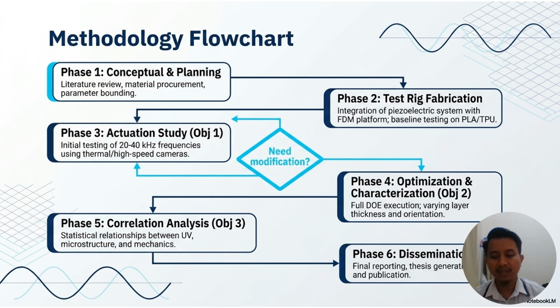Here, FDM-printed SMP samples are subjected to UV frequency from 20 to 40 kHz, with shape transformation recorded by thermal and high-speed camera. Notice the feedback loop in the flowchart. If modifications are needed to the test rig or protocol, we look back to Phase 2 before proceeding. Phase 4 is optimization and characterization, addressing objective 2.